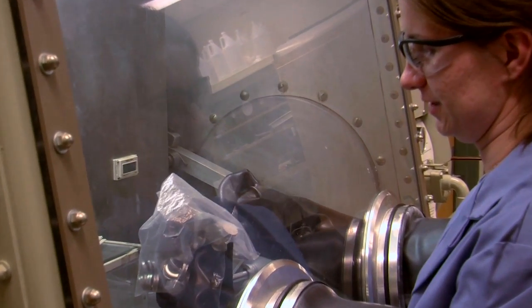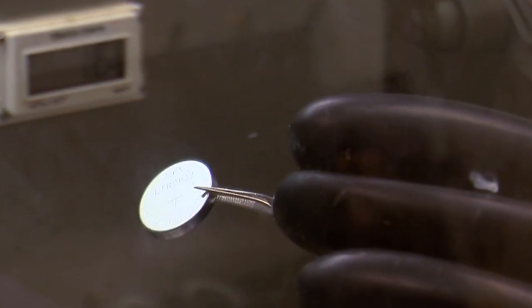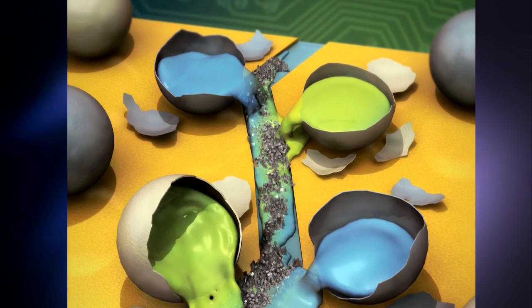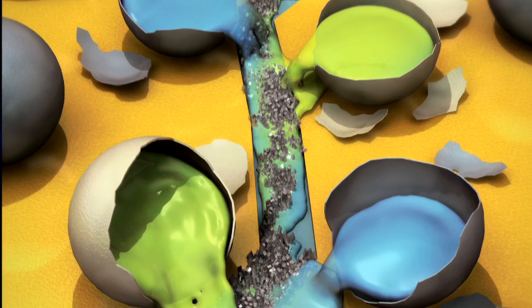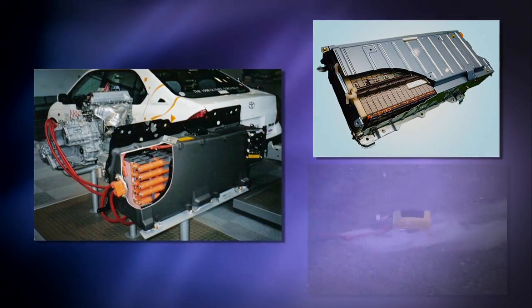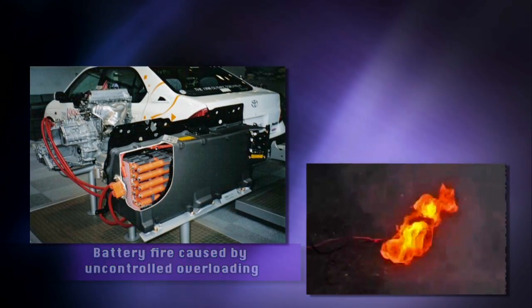We've started to translate the same concepts we looked at in terms of structural failure and restoration into things like batteries that will self-heal by restoration of simple electrical connectivity. We've put things like liquid gallium, encapsulated carbon nanotubes, and nanoparticles of silver — all for their conductive restoration properties. We're also working on ways of shutting the battery down when it gets out of control and too hot, because if a battery pack in a vehicle goes into a runaway situation, it's going to be a pretty catastrophic event. Automatically triggering shutdown in that scenario is really important.